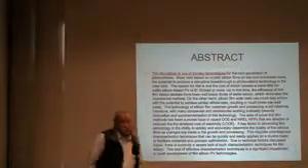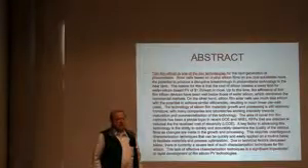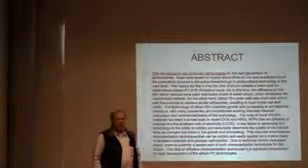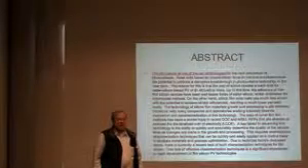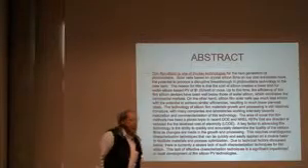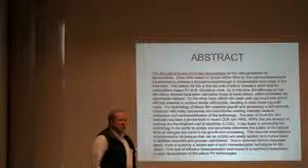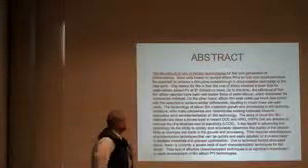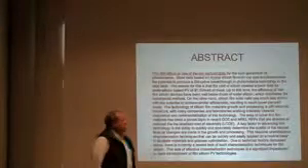And the goal here is to develop characterization tools that will allow us to characterize these thin film materials. They're much more difficult to characterize than wafer silicon for several reasons. One of the biggest reasons is that the surface and the surface recombination for as-grown wafers is much more of a dominating factor in carrier lifetime than for wafer material.